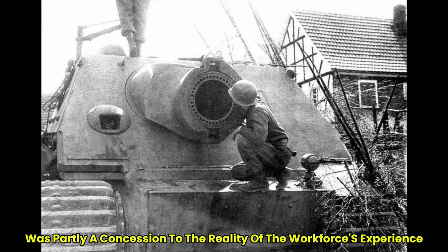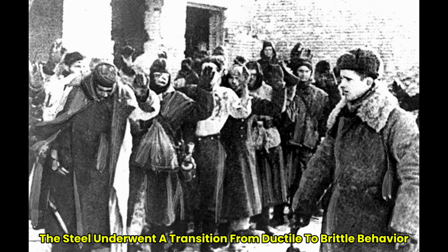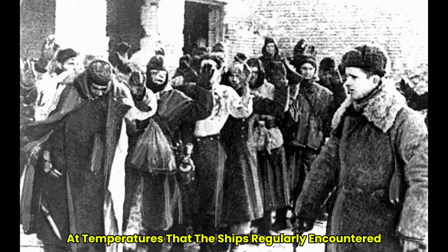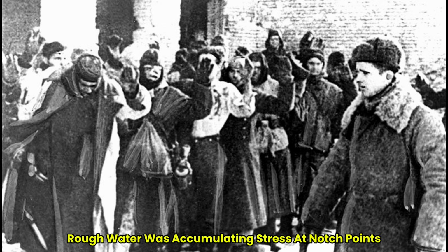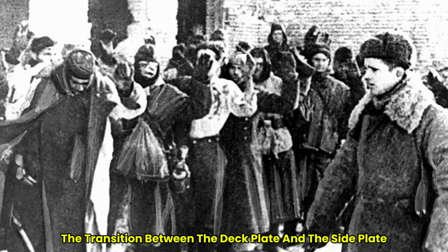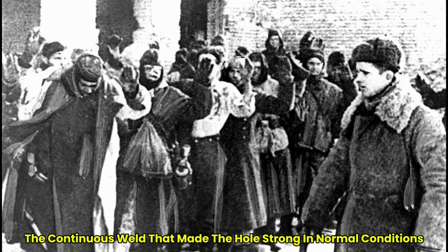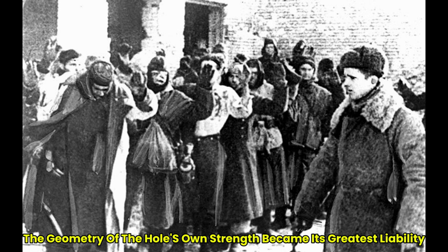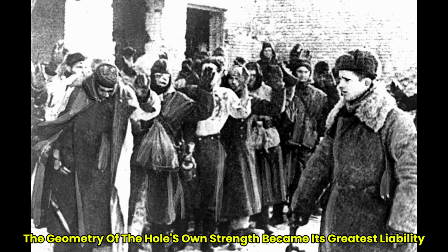They were material science. The steel used in Liberty ship hulls had a higher sulfur content than was ideal for welded construction. In cold water, and the North Atlantic and the Bering Sea are cold, the steel underwent a transition from ductile to brittle behavior at temperatures that the ships regularly encountered. A welded hull in cold, rough water was accumulating stress at notch points, corners, hatch openings, the transitions between the deck plate and the side plate. At those points, the continuous weld that made the hull strong in normal conditions became the path along which a brittle fracture could run at the speed of sound. The geometry of the hull's own strength became its greatest liability.